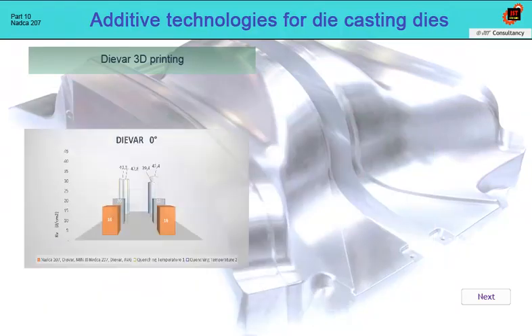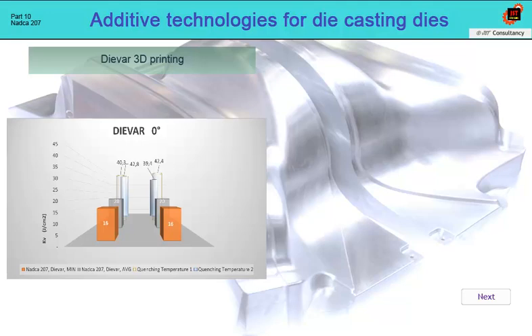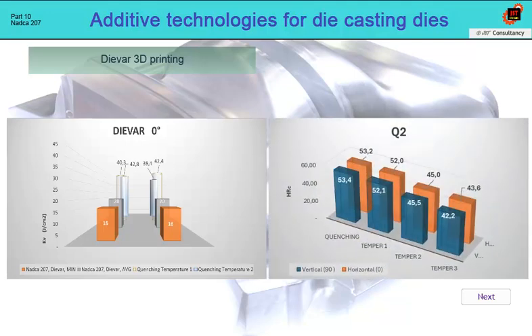As for the impact tests, we achieve values higher than for Dievar wrought steel. As for hardness, this can be seen here in this graph. The material behaves almost standardly. Only after the third tempering does the hardness decrease faster than we thought.